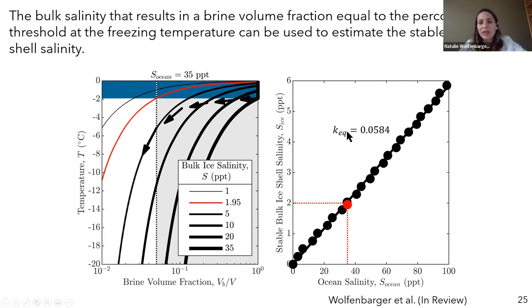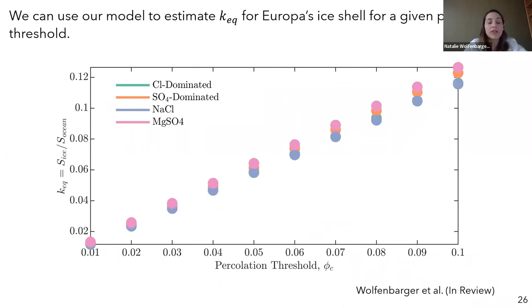So notably, this is a little bit lower than the value that I derived for the ice cores previously, but this could also be an artifact of just assuming that it's the freezing temperature of the solution as opposed to some lower temperature. But it's still compelling that we can derive this constraint, which would represent a minimum bulk ice shell salinity governed by a certain percolation threshold, which in our case is 0.05. However, we don't need to use 0.05. We can consider a range of different percolation thresholds. And so that's what we did, considering 0.01 to 0.1.